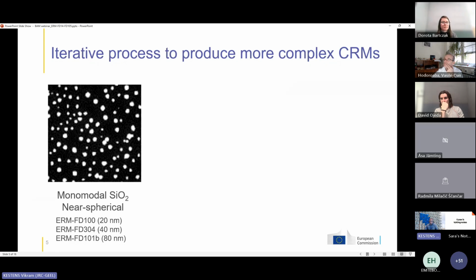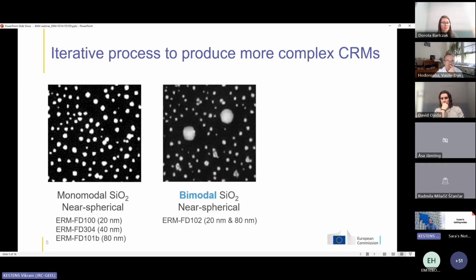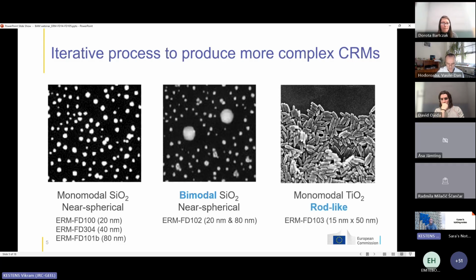And what I also would like to mention here is that in the production of nanoparticle reference materials, we had to go from, let's say, a simple approach, focusing on monomodal silica particles, to more complicated materials. For example, the next materials that we produced were not monomodal anymore, but bimodal. So for example, here this ERM FD102, where we had a mixture of 20 and 80 nanometer particles. Or at the next stage, we moved away from near spherical shapes, and we went to nanorods, such as this example here, titanium dioxide nanorods.